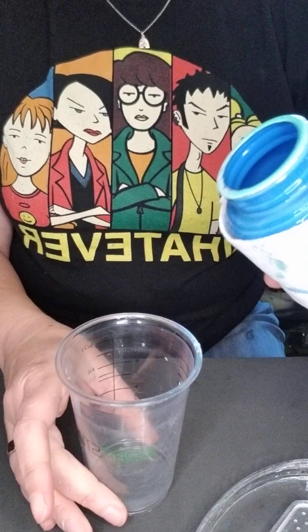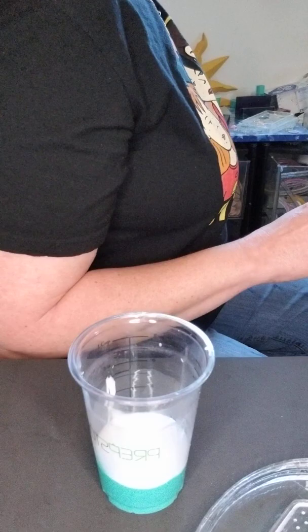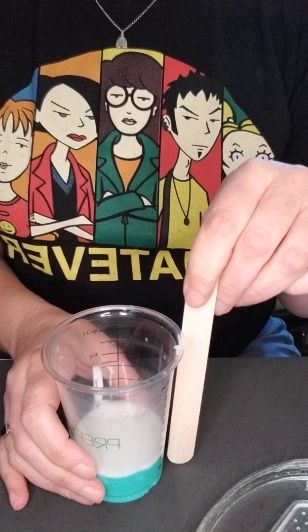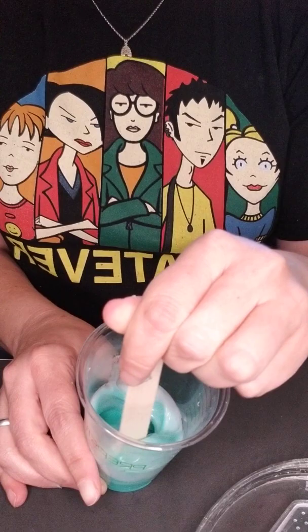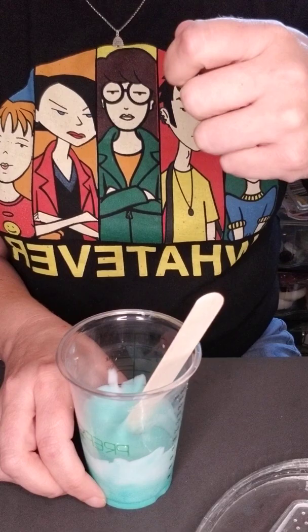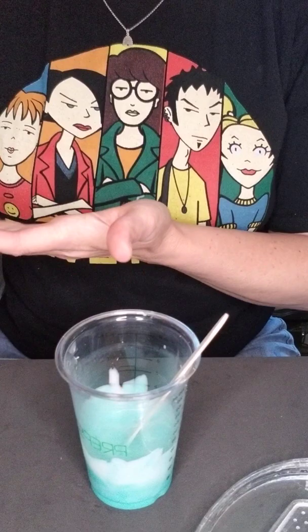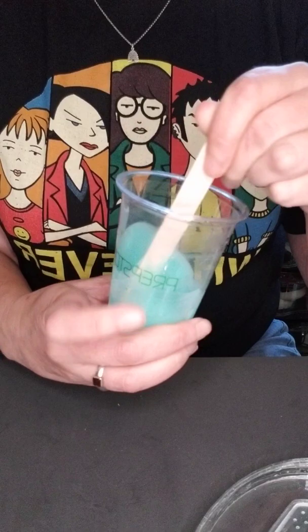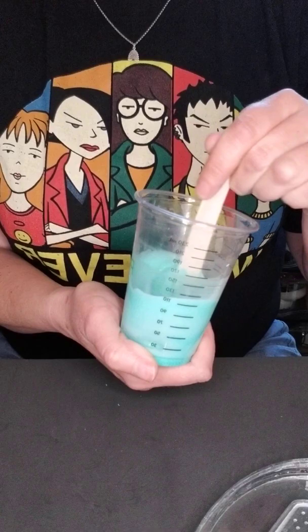We're going to mix equal parts of part A and part B, and stir with a wooden stick. For these cups, popsicle sticks are too short, so I use wooden tongue depressors — medical grade. Stir thoroughly; you don't want any white streaks or blue. Do not whip it like an egg — you will introduce more air, which is not the goal. Using a transparent cup is important so you can see coverage on the sides and edges and make sure it's well mixed.